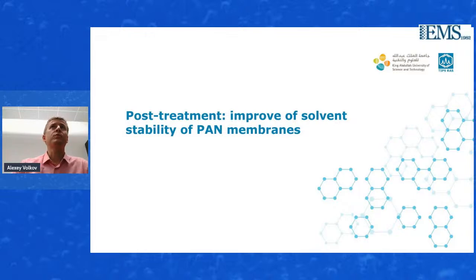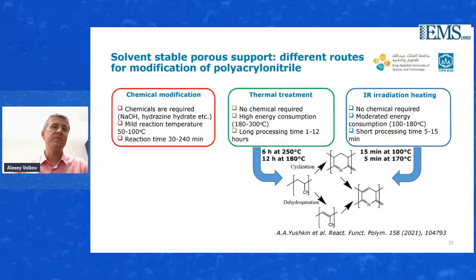But at the same time, today we have quite a good mature level for making membranes for water treatment and for desalination. But at the same time, there is still a challenging area, the area of application of membranes for non-aqueous systems. And in that regard, it's quite important to look at the materials that are stable in organic solvents. And once again, PAN is quite an interesting material because it can be cross-linked by different approaches, making the polymer and the membrane insoluble in the aprotic solvents that are usually used for the casting of the membranes.